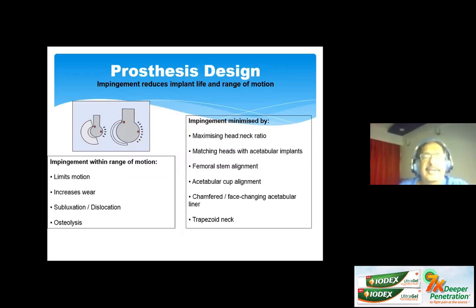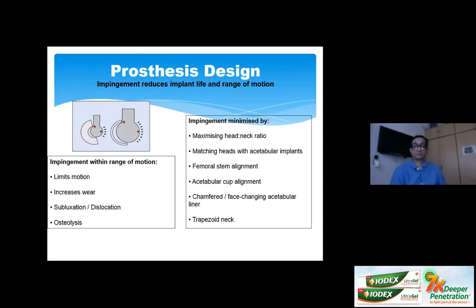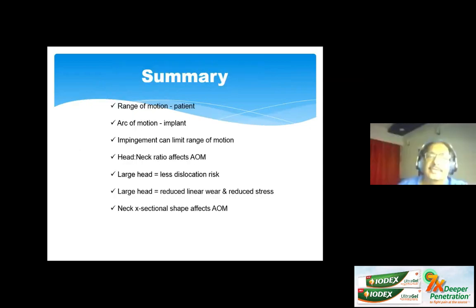So impingement within the range of movement will cause limitation of range, increase the wear, and also increase the risk of osteolysis. Impingement can be minimized by maximizing the head to neck ratio, matching heads with the acetabular implants, better femoral stem alignment and acetabular alignment, and a trapezoidal neck. So this is what we have in our control. The arc of motion will depend on the implant, and the head and head neck ratio. With a large head, as we discussed, the dislocation risk is reduced, though liner wear can sometimes be increased in large heads, and the neck shape is important.